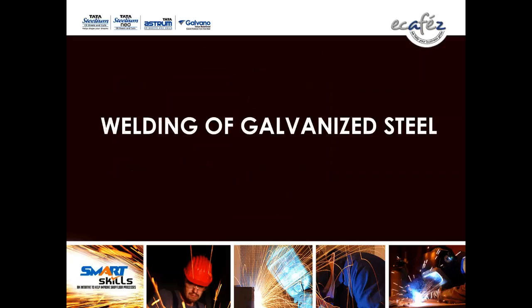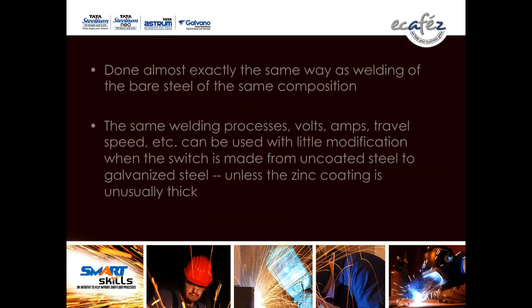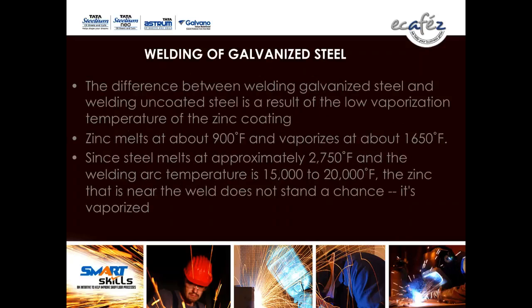Welding of galvanized steel. Somebody was asking about welding galvanized steel. It is done almost exactly the same way as welding of bare steel of the same composition. The same welding processes, MMAW and MIG, can be used. Volts, amps, travel speed, etc. can be used with little modification when the switch is made from uncoated steel to galvanized steel, unless the zinc coating is unusually thick. So, if you go for galvanized steel welding.